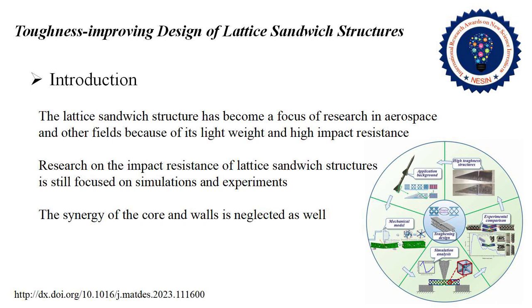When studying the low-velocity impact for lattices, some researchers found that the failure mode of lattices can be changed by the gradient structure, and this gradient lattice can enhance the crashworthiness of parts. Some researchers found that the multilayer lattice structure has a higher energy absorption effect when studying the explosion resistance of lattices underwater. Some researchers proved that filling the intracavity of thin-wall tubes with lattices can improve the impact energy absorption of tubes in the axial direction. And some researchers evaluated the deformation mode of layered hybrid lattices by the drop hammer method and the split Hopkinson pressure bar under dynamic loads.